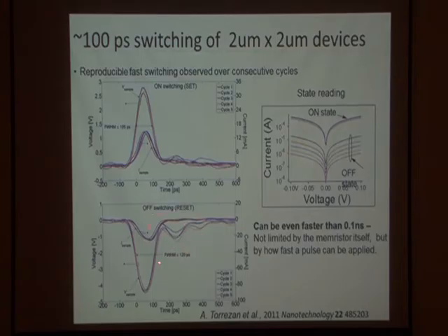And here there's something interesting. This is our pulse generator, which wasn't very great, so it always sent this kind of ghost peak right after it. But what I like about this is this. Here the device was on. This is the pulse to switch it off. Here's the current, the solid line is current. And then there was this ghost peak. And when you hit it with this ghost peak, there's no current. So this is almost like a pump and probe system. In about 300 picoseconds, you can set the device, you can reset it, and then read it. So I think this is something that is cool about this.